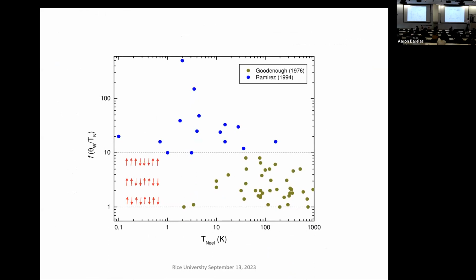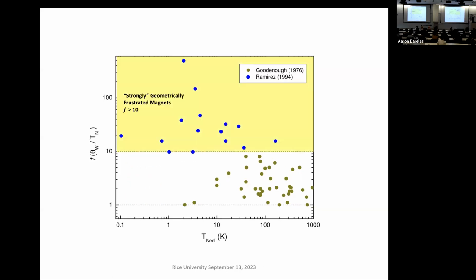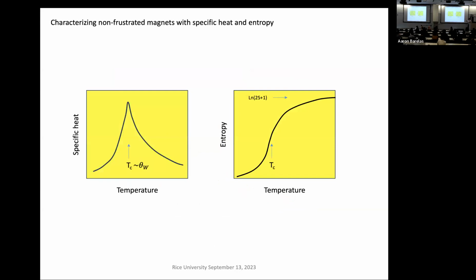That probably represents only 1% of all magnetic materials, but the idea is that most materials have this ratio, because it's unrealistic to think that for a certain lattice, when you populate it with atoms, the bonds are perfectly matched to the lattice that they find themselves on, because the lattice forms at a much higher temperature. So there are quite a few frustrated materials, and that gives us the basis for going forward. Now, I just want to say something about entropy.